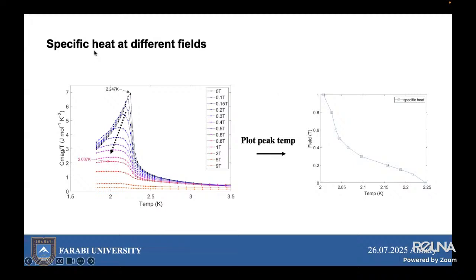And you see that this figure represents the temperature dependence of magnetic specific heat divided by temperature, measured at different external magnetic fields. From the data, they extract the magnetic transition temperature and construct a field-temperature phase diagram. If you plot the peak temperature, for example, in this diagram, the magnetic phase diagram from the heat peaks, you see that the peak temperature extracted from each curve in the left panel is plotted against the corresponding field values to construct the magnetic phase boundary. The resulting curve shows a clear downward trend, demonstrating that the transition temperature decreases with increasing field.